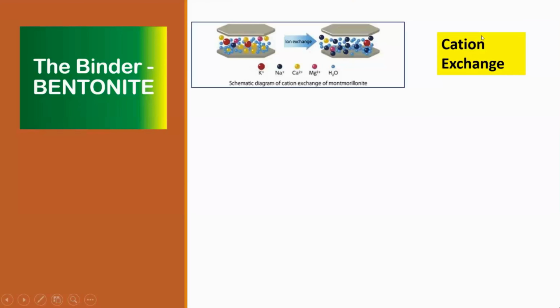Looking at it a little more deeply, we see that cation exchange can be done. So this bentonite can be either a sodium based or a calcium based or a magnesium based or a potassium based. So all of them can hydrolyze and then they can occupy this position between two crystals. Now, in the unhydrated situation, it will be like this. And when they hydrate, you can exchange the ions.